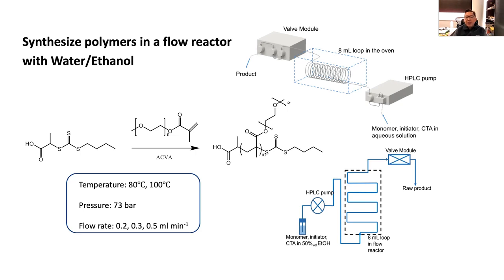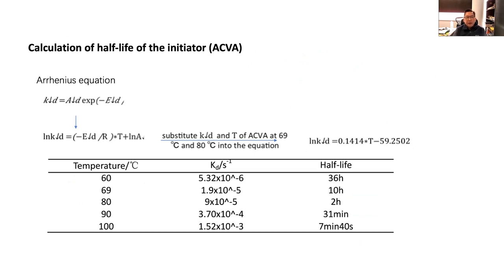So in this schematic diagram, we introduce the monomer, the initiator under various ratios together with the chain transfer agent, and then we achieve the corresponding polymer. And as you can see here, the advantage of doing things under flow is we're able to heat the system up to 100 degrees C, resulting in a half-life of about 7 minutes, whereas most AIBN type of reactions are done in hours. We can do our reaction in minutes.